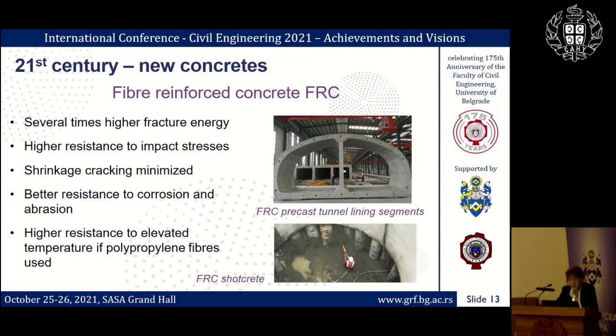So several times higher fracture energy, higher resistance to impact stresses, shrinkage cracking minimized, better resistance to corrosion and abrasion, and high resistance to elevated temperature if plastic fibers are used. Due to that, this type of concrete is usually applied in industrial floors, precast lining tunnels, as you can see here, pipelines, in repair works, in shotcrete, and now there is an ongoing research related to the application of this concrete in structures, but without any conventional steel reinforcement.